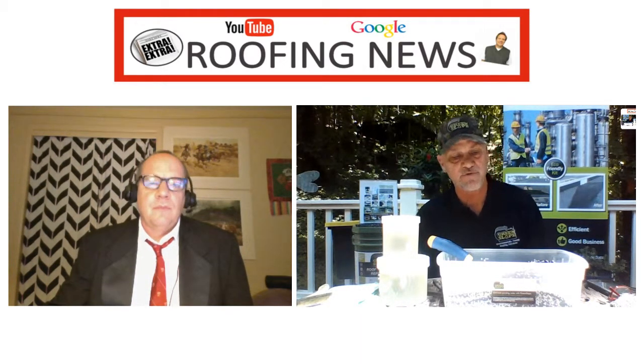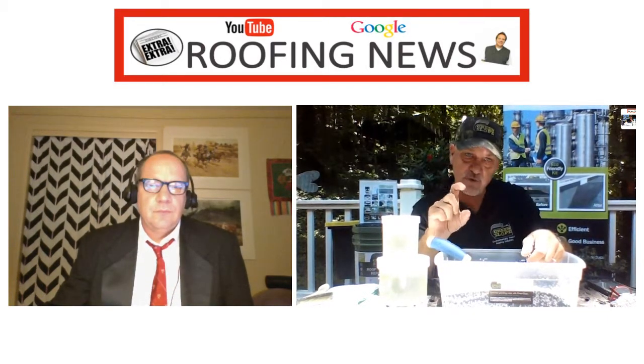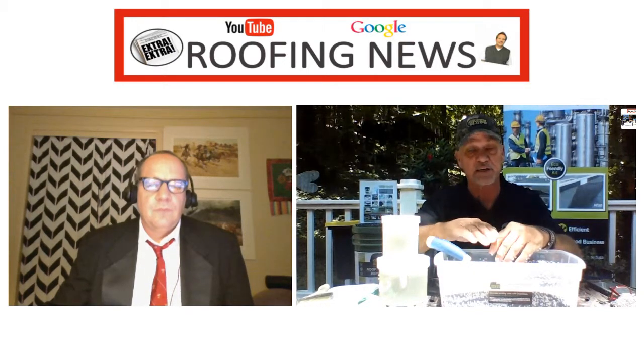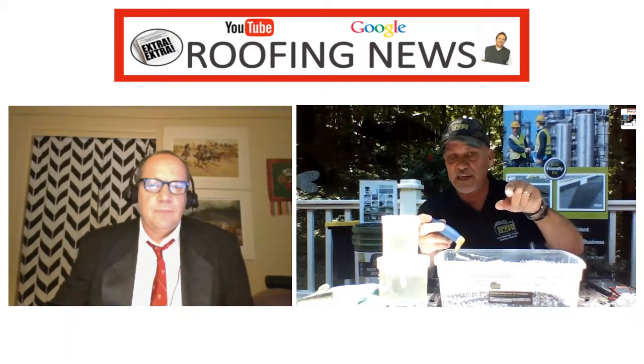Sure. It's funny, because the more contractors I talk to, the more places they find for this. Typically, for instance, pitch pans, the box you put around a penetration going through the roof system, are traditionally filled with a concrete mix for 2/3, and then a pourable sealer for the top third. Or some use a pourable sealer for the whole thing. What we found is this is ideal to fill in that 2/3 before you put your pourable sealer in. Pourable sealer is very expensive, but you really want that on the top surface. So this is instead of concrete, which leaves a dusty film, and you're never sure if the pourable sealer is going to stick around the surfaces. You don't have that issue with Green Slope.